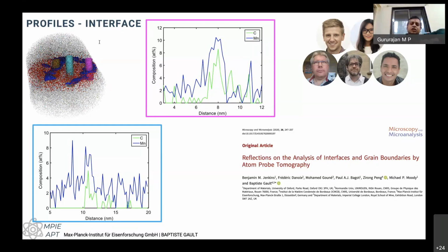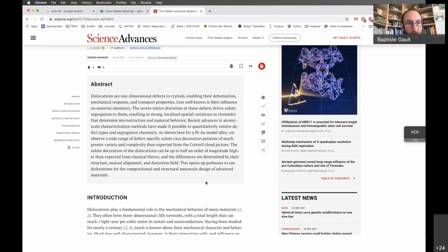So the kinks in dislocation is because it is sort of BCC kind of system, is it? Yes. They have a double kink kind of mechanism. Exactly. But also, most of the dislocations that we've been able to image are never straight lines like this, right? That's one of these textbook lies, I guess. So do you also then see differences in segregation because the nature of the dislocation has changed? Yes. You can look at that paper.